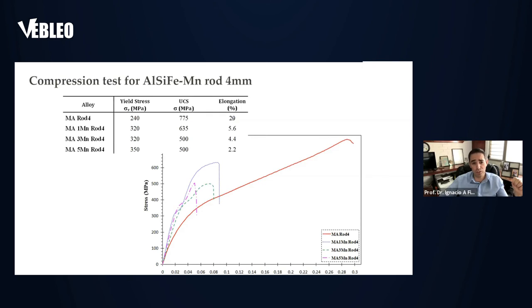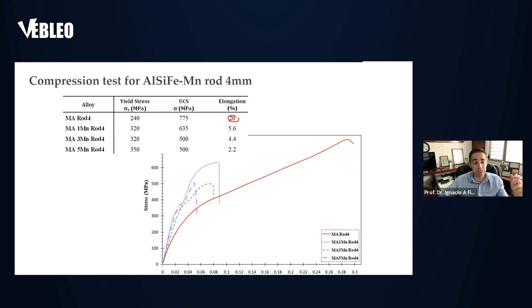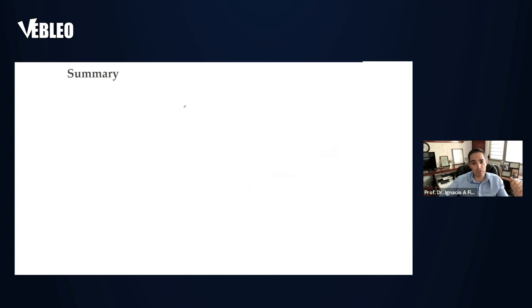For the 4 mm rod, one of the best results shows about 20% elongation. However, when we add manganese in the 4 mm configuration, it drops both the elongation and the UCS. This was associated with the formation of those needles that the manganese produced together with the intermetallic — those sharp needles are stress concentrations in the sample.